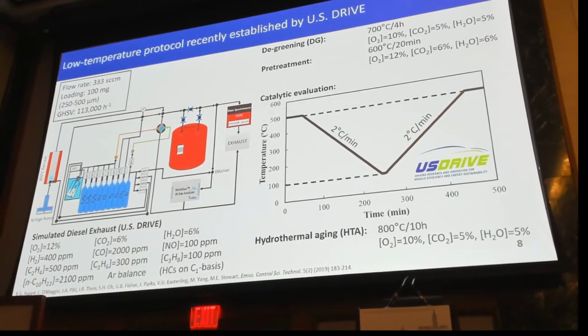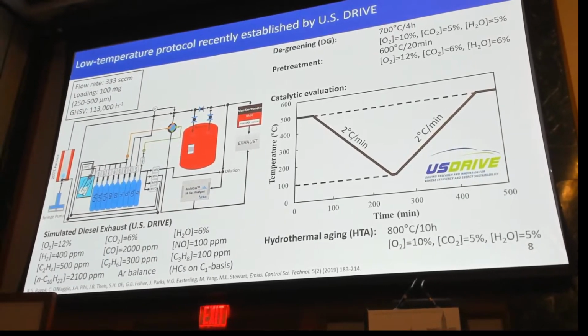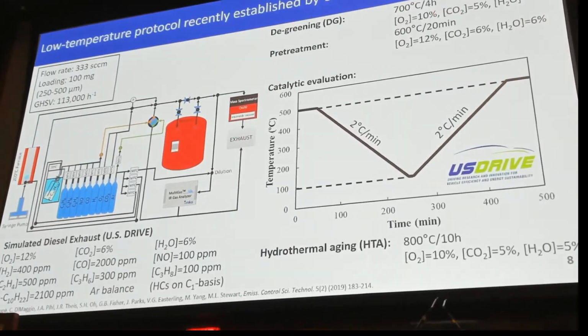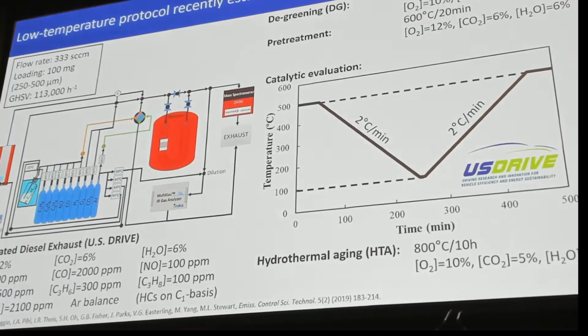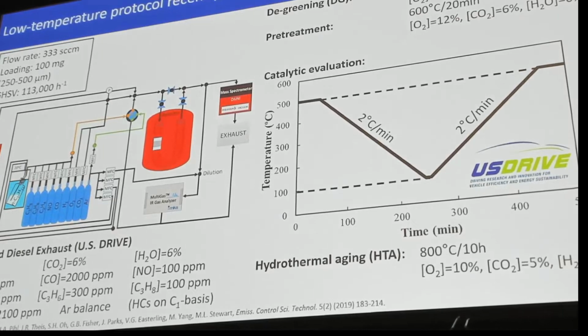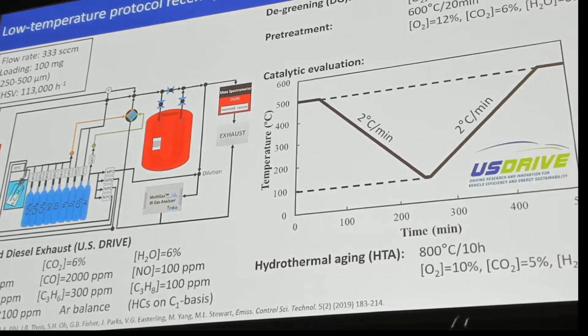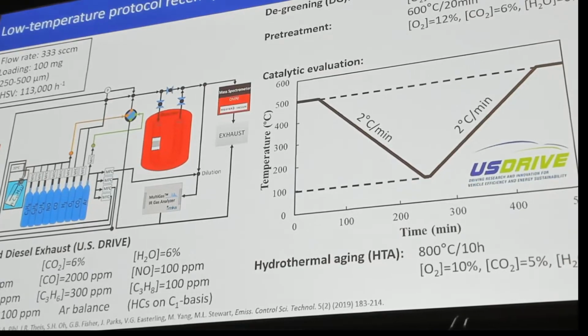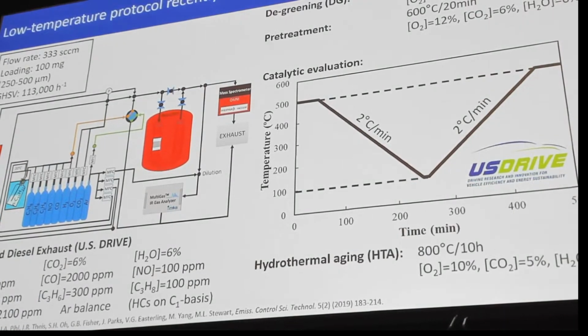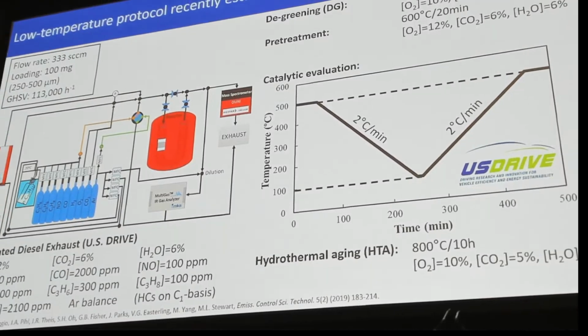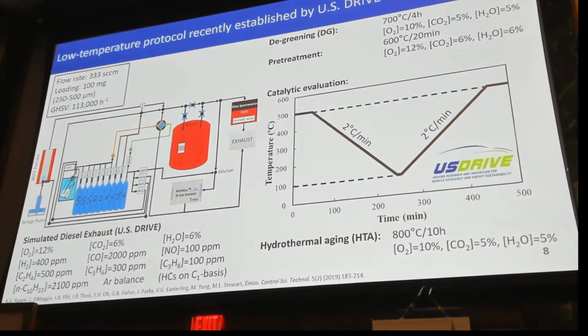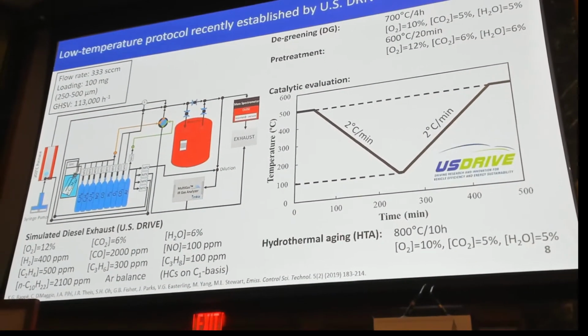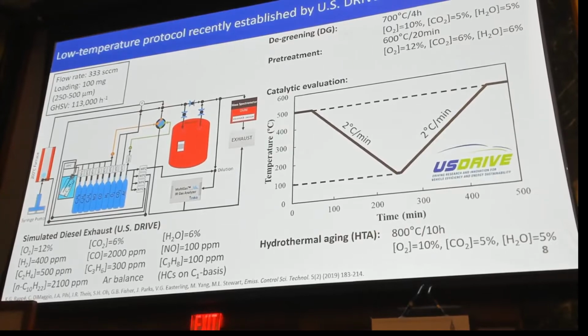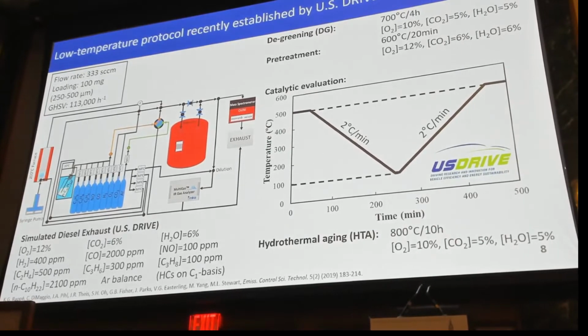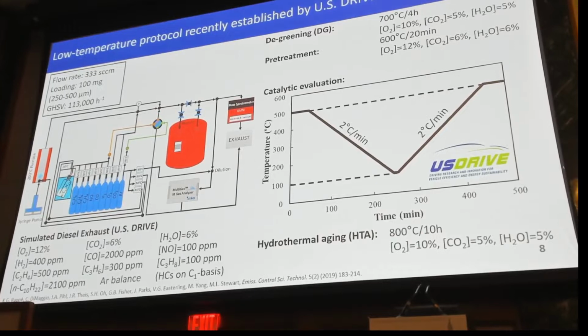The catalyst is degreened at 700 degrees C for 4 hours, and you can see the conditions here. The pretreatment at 600 degrees C for 20 minutes. And then the catalytic evaluation involves cooling down to 100 degrees C and then heating back up to 500 degrees C with a ramp rate of 2 degrees C per minute. So we want to challenge our catalyst, so we hydrothermally age them at 800 degrees C for 10 hours. And this is the condition that we use for hydrothermal aging.